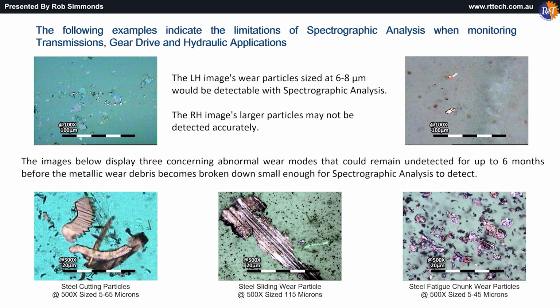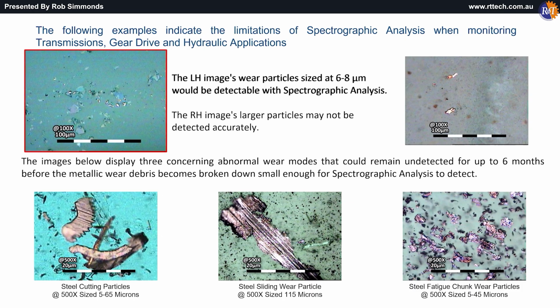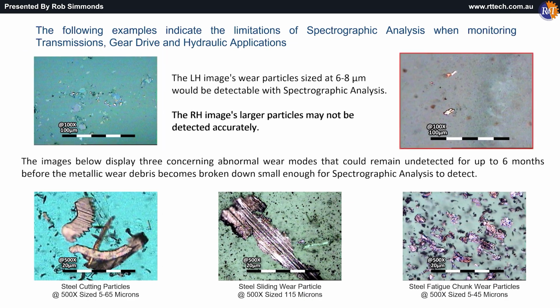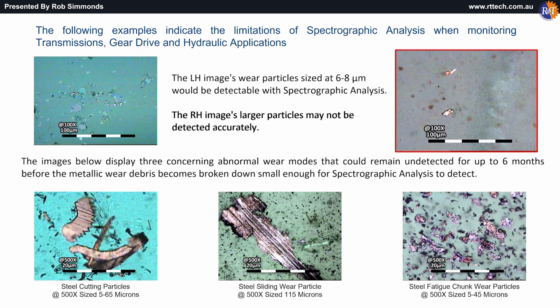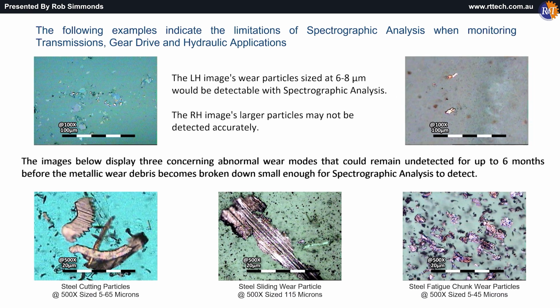The following examples indicate the limitations of spectrographic analysis when monitoring transmissions, gear drive, and hydraulic applications. In the left-hand images, wear particles sized at 6 to 8 microns would be detectable with spectrographic analysis. In the right-hand images, larger particles may not be detected accurately. The images below display 3 concerning abnormal wear modes that could remain undetected for up to 6 months before the metallic wear debris becomes broken down small enough for spectrographic analysis to detect.